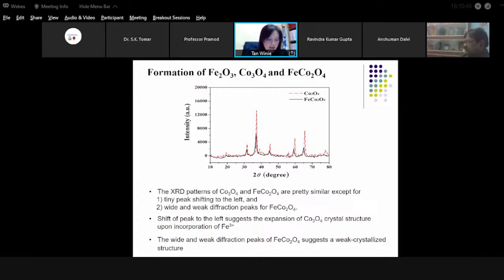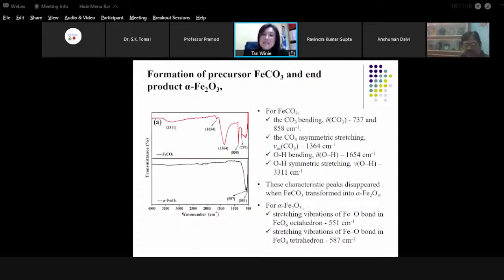On the other hand, we can see that the weak and wide diffraction peaks for the iron cobaltite suggest a weakly crystallized structure. This weakly crystallized structure can help in expanding or contracting, which can then facilitate the intercalation of charges during the electrochemical reactions. Okay, and we also counter check the structural properties using the FTIR.